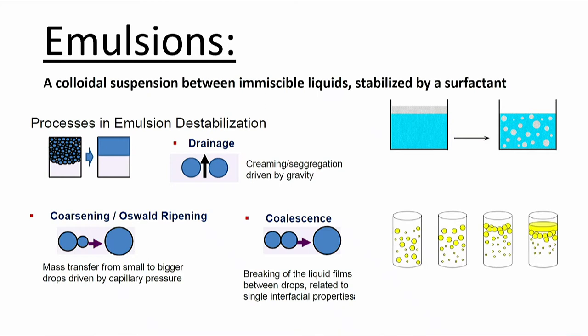immiscible liquids, then you could have other methods of migration. Micelles could transfer mass from one droplet to the other. So Ostwald ripening is happening, it's ubiquitous, also for immiscible liquids. And finally, coalescence, that is the case where you have two droplets that get into one because of breakage of the plateau border between the two. So these are the mechanisms that basically drive emulsion stability.